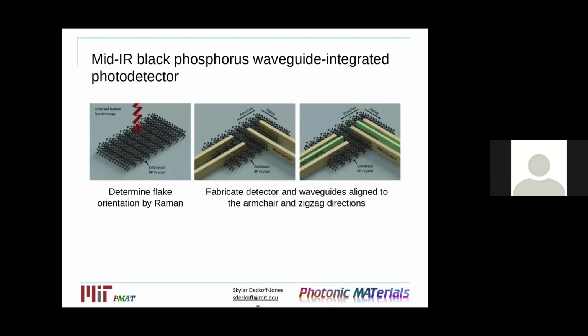And next, I want to introduce our work on black phosphorus-based mid-infrared photodetectors as well. So similarly to the graphene, where we were able to start with a layer of graphene and then alternate layers of glass and graphene, black phosphorus, for those of you who aren't familiar with it, is an interesting 2D material because it shows strong in-plane anisotropy. So you actually have these preferential armchair and zigzag directions where you have very different properties with regards to absorption coefficients and mobilities. And so you can envision that it's very important to know the orientation of a waveguide-integrated photodetector relative to the crystalline orientation of the black phosphorus.